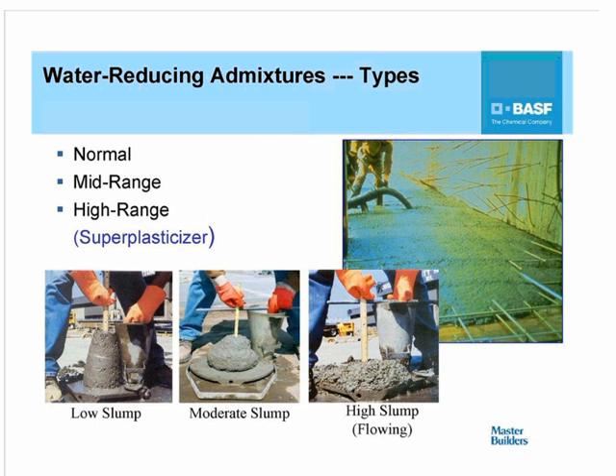And there are different types of water-reducing admixtures. We have the normal types, which will fall under the ASTM C494 Type A category. And then we also have high-range water-reducing admixtures that fall under the ASTM C494 Type F category. Now, in between, we also have the mid-range water-reducing admixtures, which at this point in time are not covered by any one particular ASTM C494 category, but most of them do meet the Type A category.